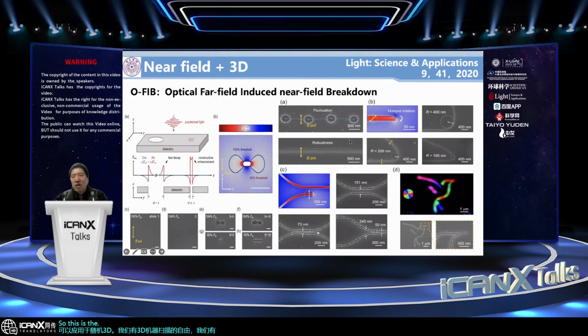This is an example of how we use the technology to make a single line. They are very narrow. What we demonstrate here is 15 nanometers. In the very latest experiment, we already realized 7 nanometer spatial resolution. So this is 3D fabrication, and the fabrication accuracy is very high, down to the level of 7 nanometers. It means this is a very good technology. So we named the technology OFIB. The full name is optical far field induced near field breakdown. In abbreviation, we call it optical FIB.